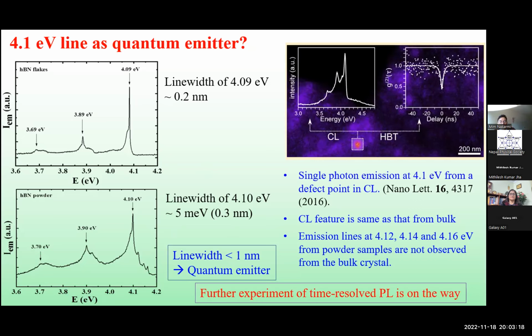And because the line width is so small, this could be a quantum emitter. And another group has reported a similar result from boron nitride. Their result was they also observed 4.1 eV and its phonon replica, whose shape and peak positions are exactly the same as we found in the photoluminescence. But how they observed it is they scanned the whole material and found one very small spot. See, the scale here is 200 nanometer, so it could be even less than 100 nanometer. So in one spot, they observed that emission.